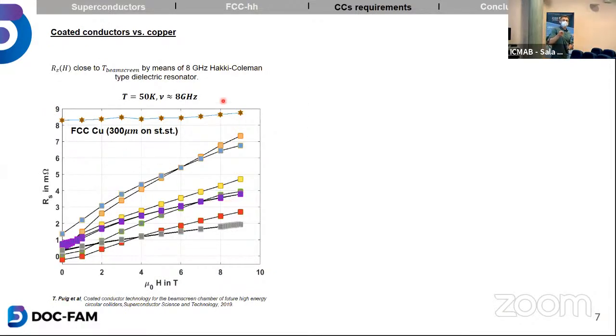I mentioned copper is being used in the Large Hadron Collider, so it's a direct competitor of superconductors. That's why we had to measure the surface resistance as a function of magnetic field of copper in comparison with several coated conductors. You might be surprised: why do we suddenly see a resistance for superconductors? Well, it's not the normal resistance, it's the surface resistance. As I mentioned, or maybe I didn't mention it, the mirror charges oscillate with a very high frequency, around 8 gigahertz, and thus dissipation occurs. Only in the regime of direct current do superconductors not have dissipation. Actually, at high frequencies, they do have a resistance.